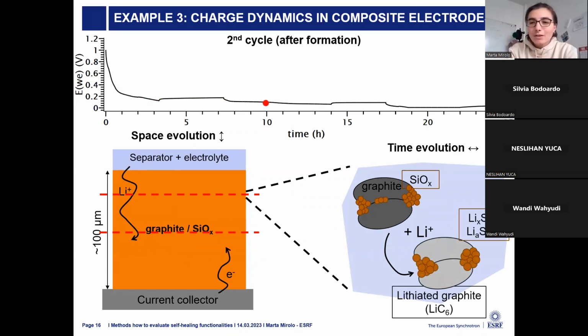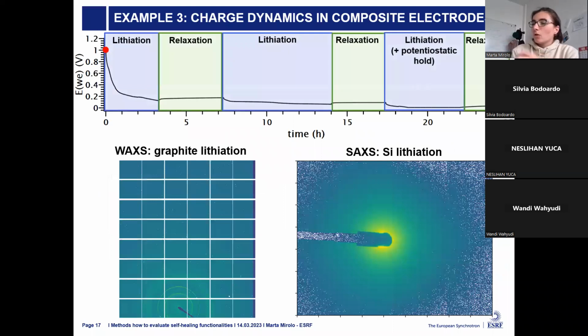Are they lithiating the graphite? Are they lithiating the silicon? What happens during relaxation of this composite? So to study these composite materials, we performed quasi-simultaneous wide angle and small angle X-ray scattering.